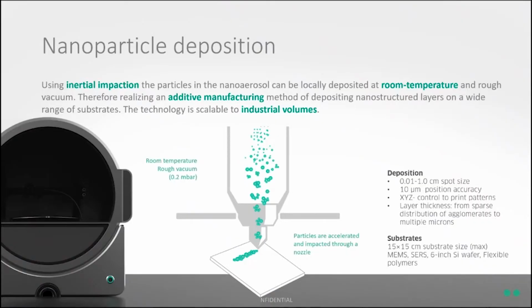So the final step is really the deposition step, where we are 3D printing in an additive way the nanoparticles on the support. So we developed a special printing process, which is taking place at rough vacuum, so 0.2 millibars. The printing stage is 15 by 15 centimeters at the moment. We have full control over X, Y, and Z. The position accuracy is 10 micron, and the spot size can be varied between 0.01 and 1 centimeter, depending on the printing head that we are using.